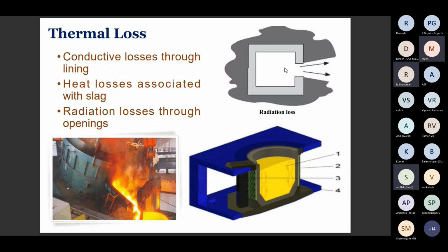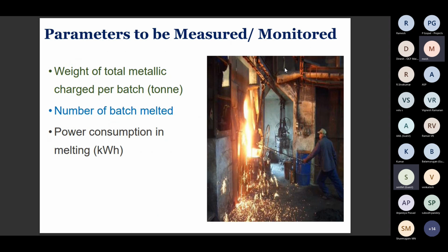So these are the thermal losses due to conductive losses through the lining, heat losses associated with the slag, and radiation losses through the openings. Next. Some of the parameters to be measured and monitored: weight of the total metallic charged per batch, the number of batches melted, and the power consumption in melting, that is kWh. These parameters are to be monitored and measured regularly. Next one.